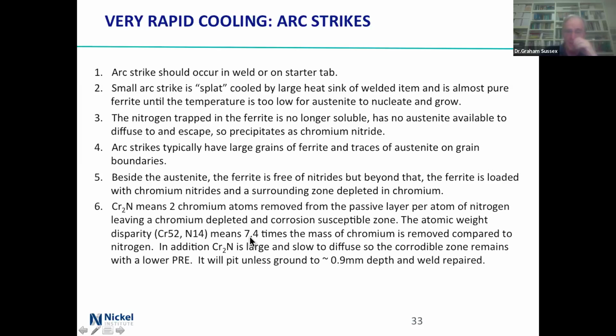And 7.4 times the mass of chromium. I thought I'd put in the sums just to get some idea of just how bad it is. And chromium nitride is actually quite large and quite slow to diffuse, so it stays put right next door in the lower PRE zone. And it'll pit. And people have done the experiment, and you need to go down almost a millimetre in depth to get away from the zone where it needs to be repaired.